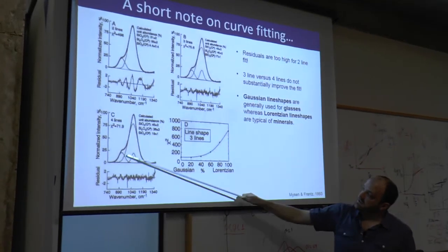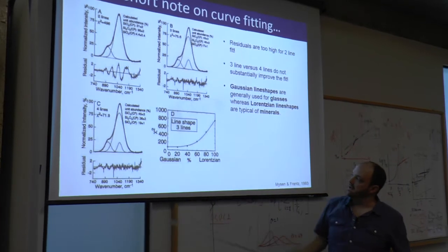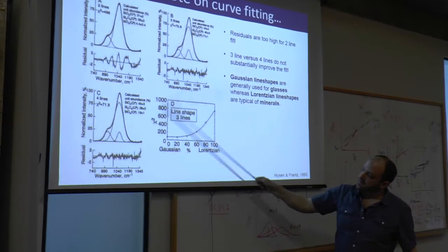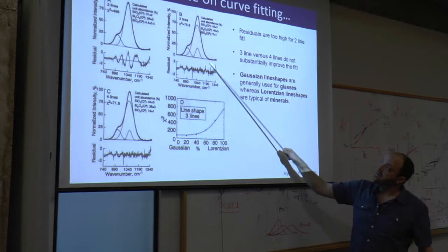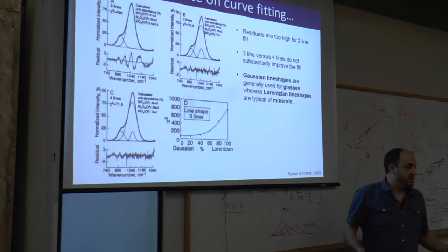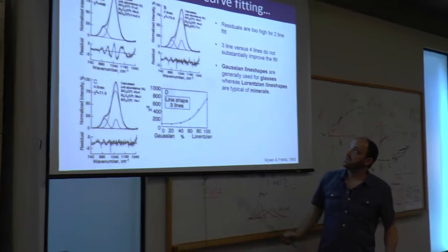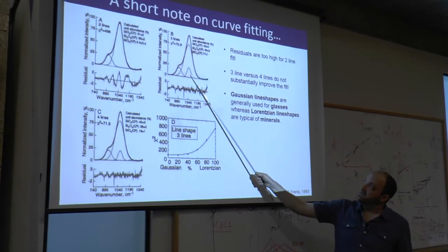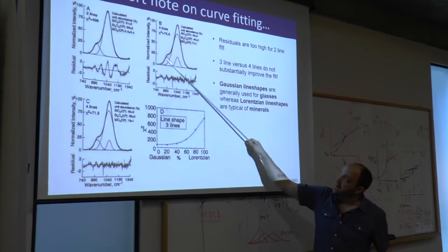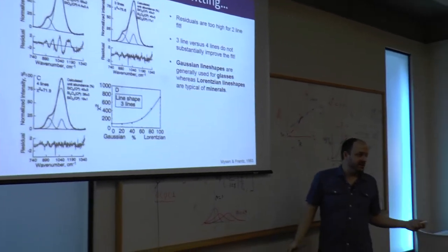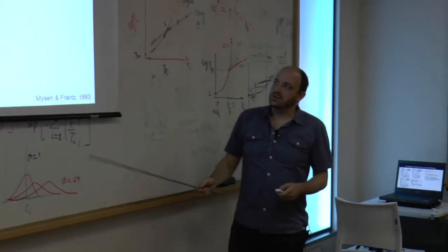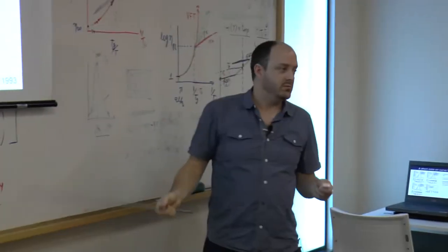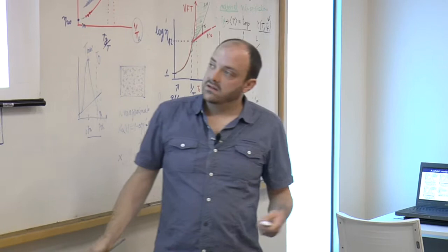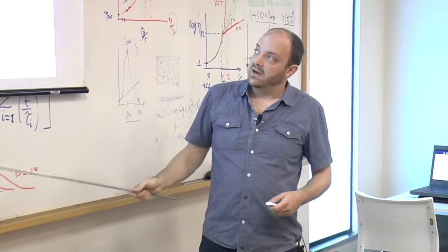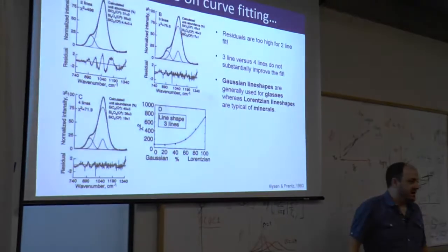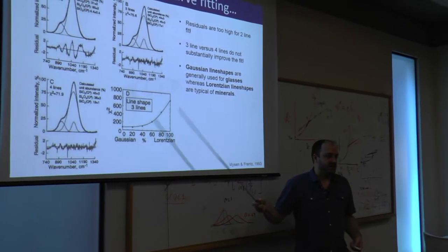So in B and C here, we have 3 lines and then 4 lines. And you can see that the residual doesn't really improve as you increase the number of bands. So when in doubt, keep it simple. I would just use 3. There's another problem with this fit, that you have this one tiny guy under another big peak. Usually that's an indication that it's probably not the best fit and that you need another peak in there as well. But you shouldn't just fit a small peak under something big and wide because you need to fit the spectra.